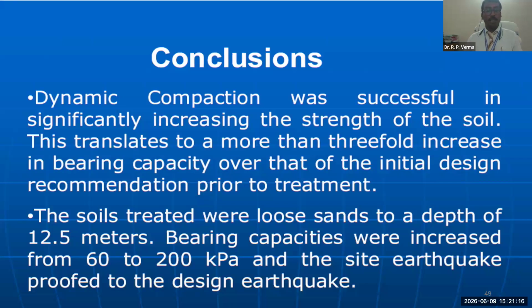To conclude this first case study, the dynamic compaction program achieved an overwhelming success. It successfully densified loose granular sand layers all the way down to a depth of 12.5 meters. Looking at the engineering metrics, the soil load bearing capacity experienced a more than threefold increase, skyrocketing from the initial 60 kilopascals to a robust 200 kilopascals.